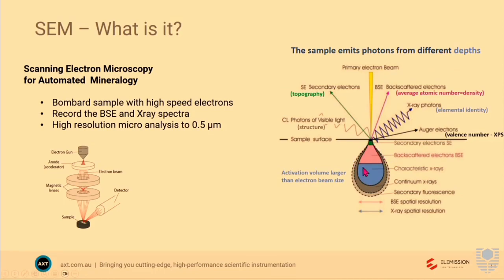The backscattered electrons come from within this activation volume here. The backscattered electrons give you the average atomic number of what you're analysing. If you are analysing a mineral, each mineral has a chemical formula, so it's got a set combination of chemicals, and if you add up all the electrons in that mineral, it's an average number of electrons. So by looking at the BSE, it gives you the average density of what you're looking at. You can have more than one mineral with the same density, but it's using the density of that mineral to define one aspect of the mineralogy.